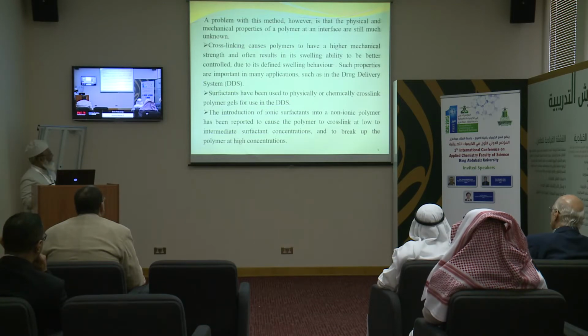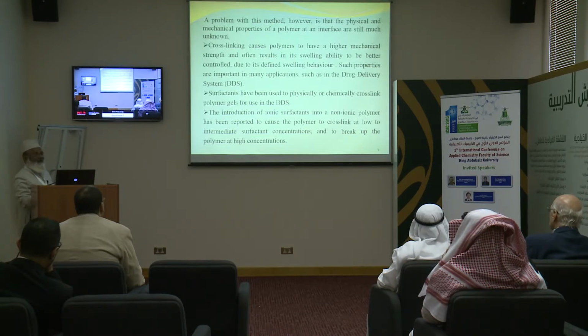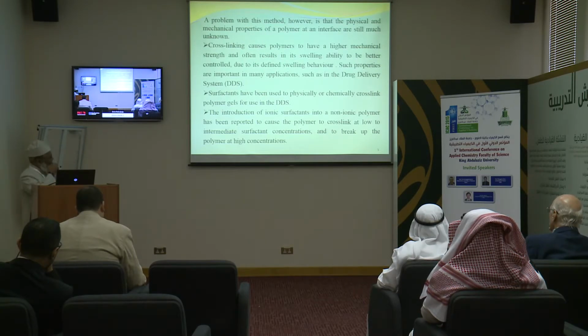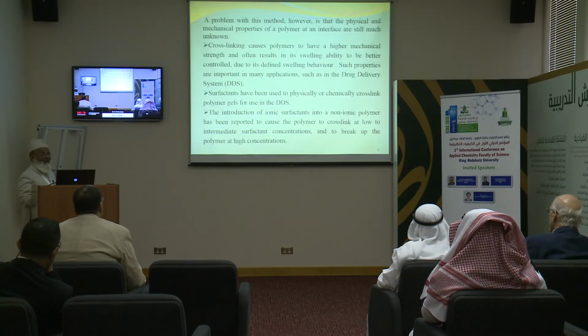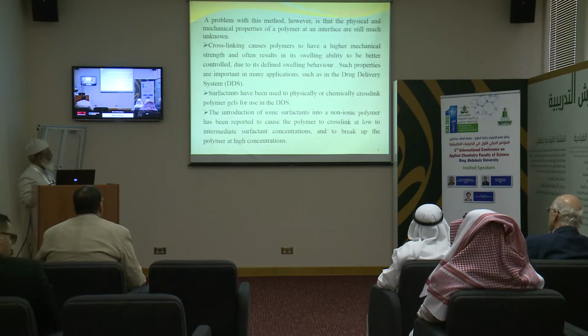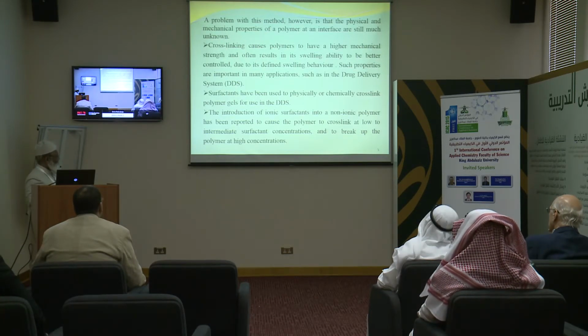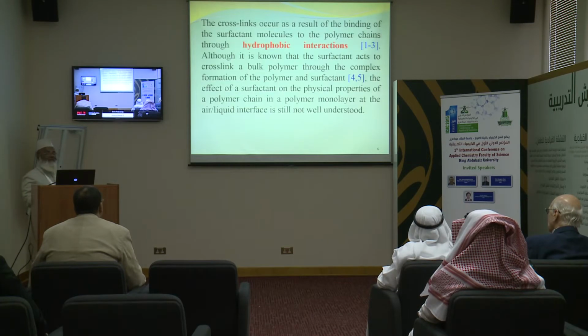Cross-linking basically causes polymers to have a higher mechanical strength and often results in their swelling ability being better controlled due to defined swelling behavior. Such properties are very important in drug delivery systems. Surfactants have been used to physically or chemically cross-link polymer gels, which are used in drug delivery systems. However, the introduction of an ionic surfactant into a non-ionic polymer has been reported to cause the polymer to cross-link at low to intermediate surfactant concentration, and also to break up the polymer at high concentrations.